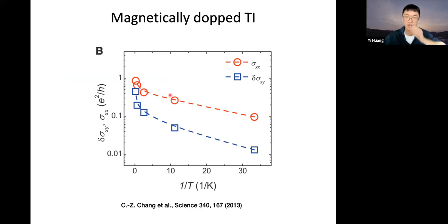They observe an activation energy, although it's only 3 points, so maybe it's not conclusive. The slope of it, I believe, corresponds to temperature less than 1 K. However, they theoretically predict, using some DFT calculation, that the band gap should be like 30 milli-electron volts. So the difference is quite big. It's more than 100.